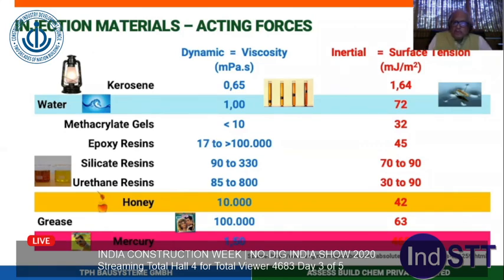If you see, water is having a viscosity of 1. And water can penetrate, water is what has already penetrated. So we have to have materials very close to the water penetration so that we can counteract the effect. Gels are very close to water. They can penetrate and their viscosity is less than 10 mPa.s. When you talk about epoxy resins, you have a very wide range of epoxy resins. So every epoxy resin is not for injection.